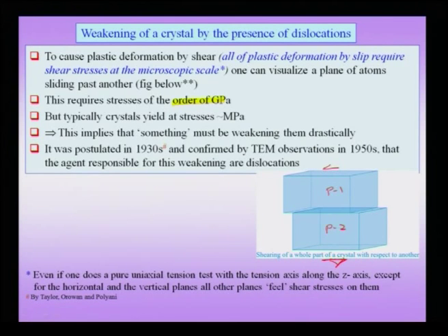It is important to note that all plastic deformation by slip requires shear stresses at the microscopic scale. Even though in a uniaxial tension test at the macroscopic level we are applying a tensile force, at the microscopic level shear stresses are required for plastic deformation by slip. But we have already seen that crystals typically yield at the order of megapascals, tens or hundreds of megapascals. That means that something is weakening the crystal drastically.